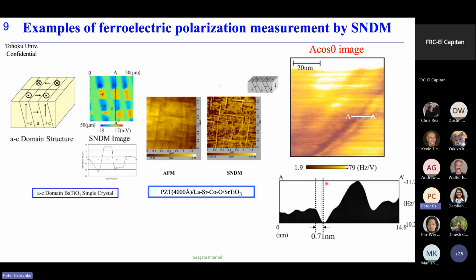And if you define the resolution of the microscope, this SNDM, when we measure the ferroelectric domain in ambient condition, the resolution is sub-nanometer order. So the resolution of SNDM is sufficient to resolve the very tiny bit, small bit, if we use ferroelectric material as a data storage device.